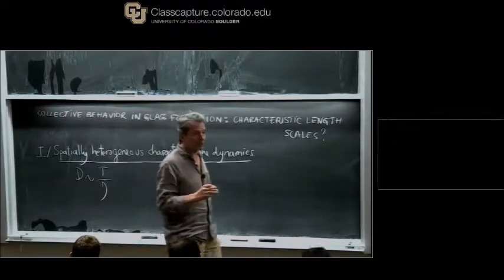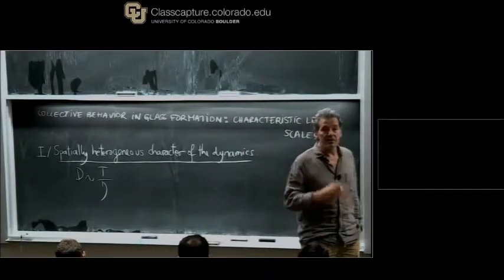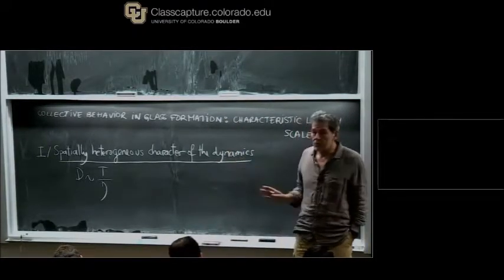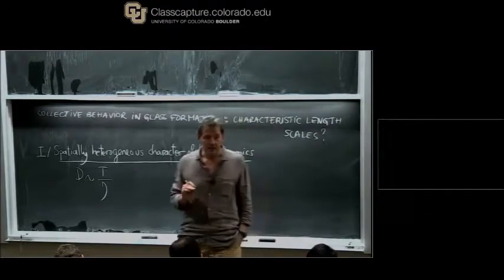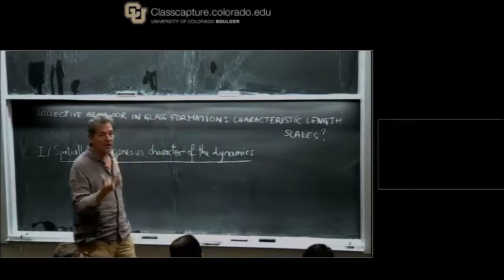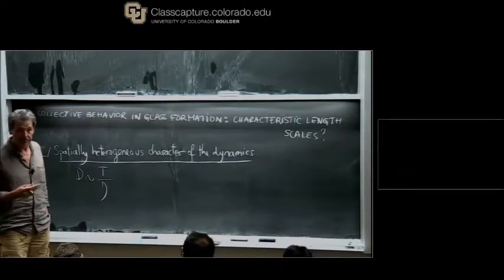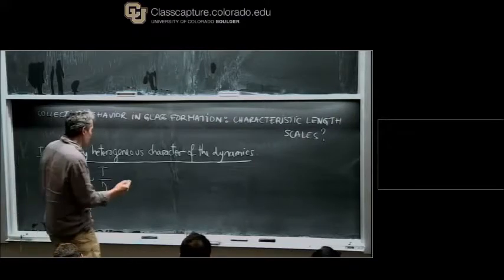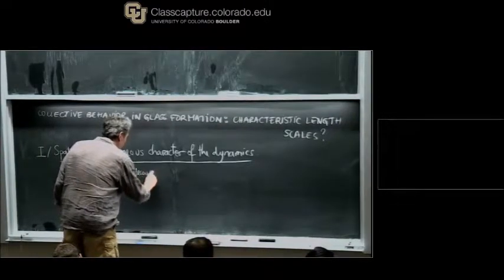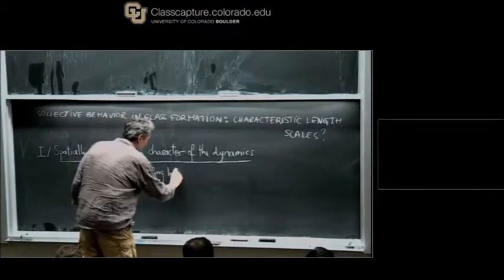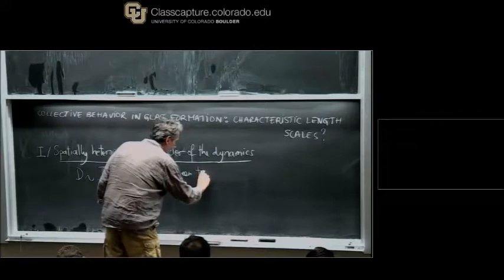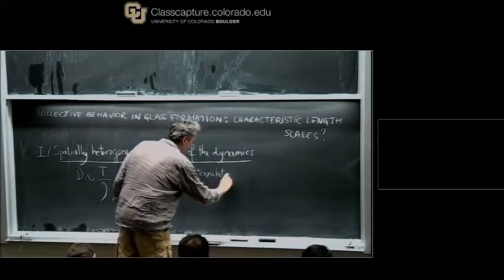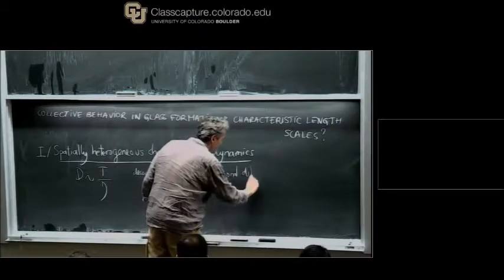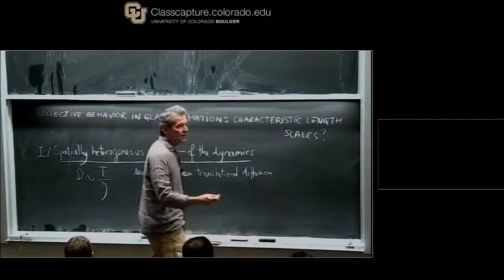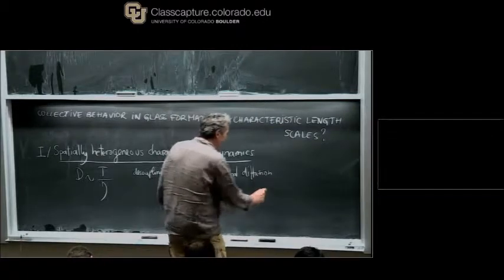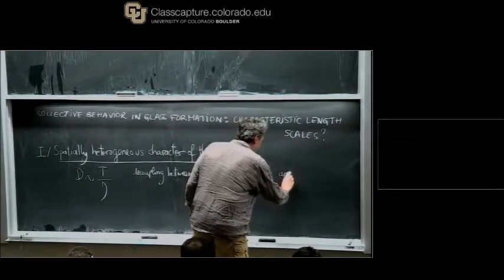Below some onset temperature, you see a deviation between the temperature dependence of those two quantities, and a deviation which is significant, not just a factor of 2 or 3. It can be 2 or 3 orders of magnitude at Tg. So there is a kind of decoupling between translational diffusion and rotations and viscosity. It is still a slow process, but it's just a little bit faster, by a couple of orders of magnitude, than viscosity.